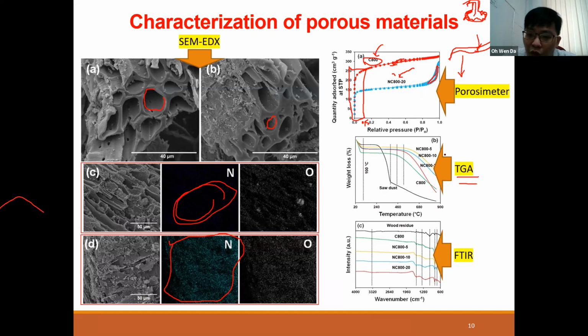So what I answered is that it's important because for the activated carbon that you have, after adsorption, the next step would be regeneration. And one of the most common regeneration methods is thermal, which means you use heat to regenerate the activated carbon. So when we conduct this TGA study, we are actually testing the stability of the adsorbent towards different temperatures. If the temperature study shows that your adsorbent is not stable after 200 degrees Celsius, this will imply that your adsorbent cannot be used for thermal regeneration.